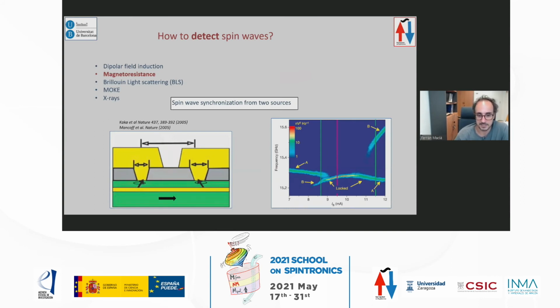One of the nice experiments is that if you pass current in one contact, this is the magnetic layer, you excite spin waves, and you excite spin waves in another one, and you can read in the same nano contact, and you can see that both synchronize through the spin waves. So there's some constructive interference, and that was shown about 20 years ago.